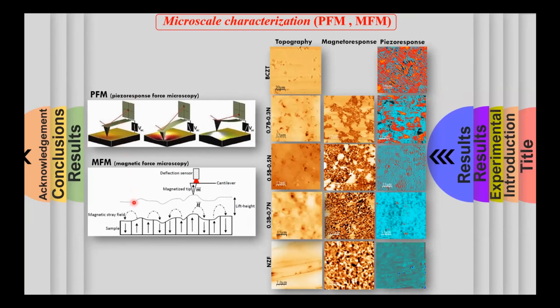the non-contact two-pass technique. In the first pass, the magnetized tip scans the surface, then it is lifted by a predetermined height. In our case, it was 50 nanometer. And in the second pass, the tip probes the magnetoresponse. Here, as we see, strong magnetic contrasts were observed in all the composites. Of course, this is attributed to the magnetic nickel zinc ferrite phase in the composite, and it attests the magnetic property at the microscale.